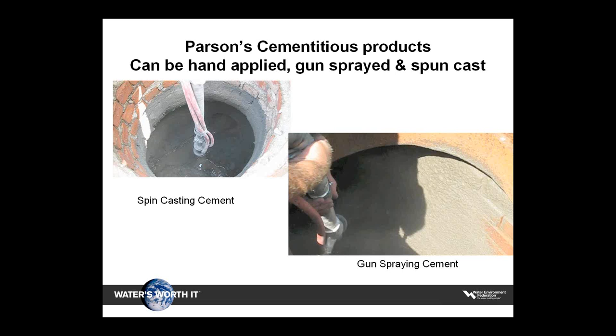By far the best and most cost-effective means of providing structural integrity to either old, poorly constructed, or deteriorated manholes is with the application of a high-strength cementitious lining. Parson offers a complete line of these products that can be hand-applied, gun-sprayed, or spin-cast in place. Parson MH Liner is our Portland cement-based product, microsilica enhanced, fiber reinforced, that can be applied up to 3 inches thick per coat.